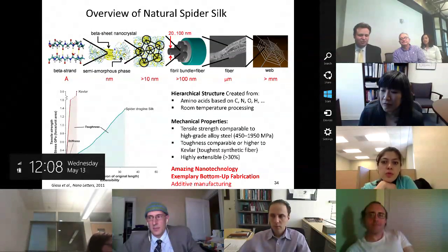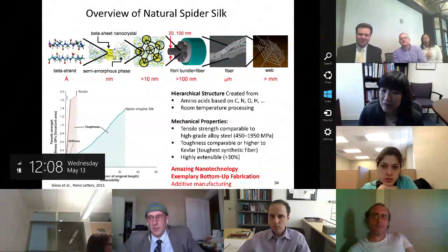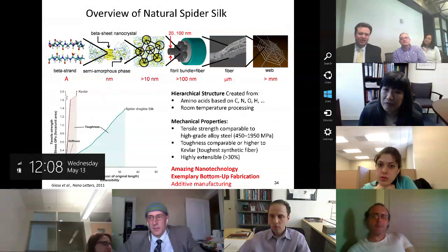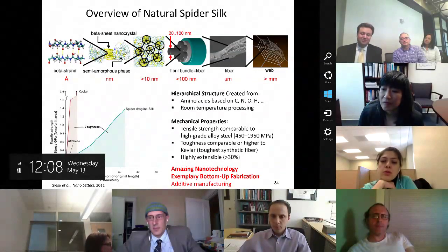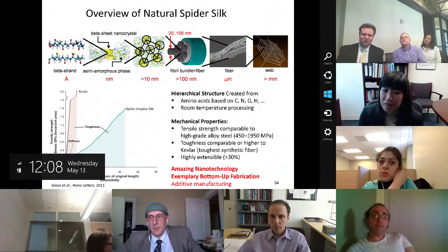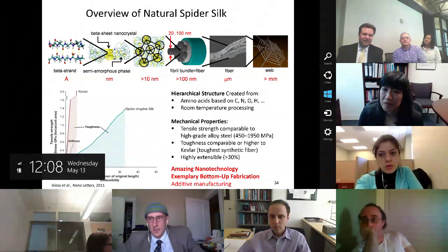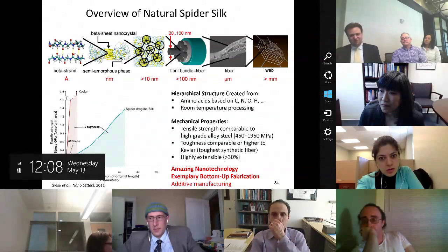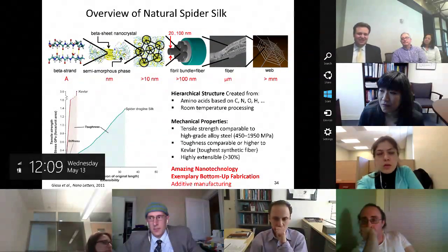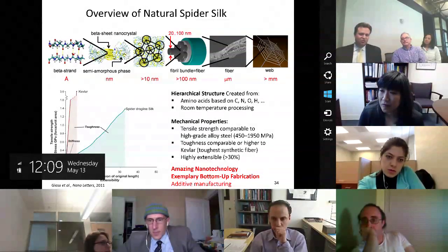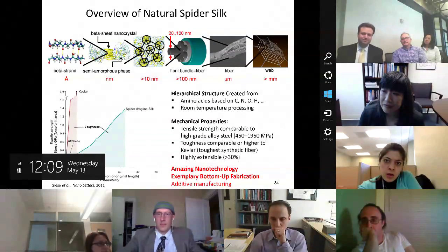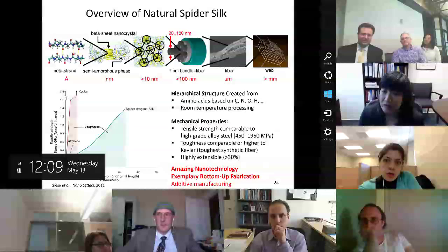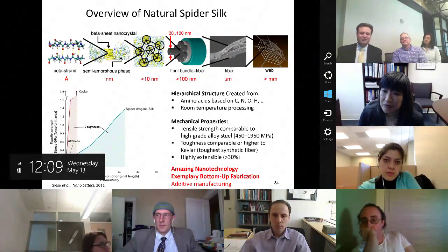So what I'm trying to say is that this approach will not work for every single protein material. It will work for silk and silk-like proteins, but if you're moving into even collagen, which is another thing we're working on, the approach has to be modified. This is the limitation of any coarse graining: it's highly dependent on the material. There's no recipe for every single material, every single sequence out there. But if you look collectively at the work we've done, comparing collagen versus silk, elastin, and other materials, you can see how a rational approach can be found. But the computer won't do it alone. We need the insight from the person running the simulation rather than the model.